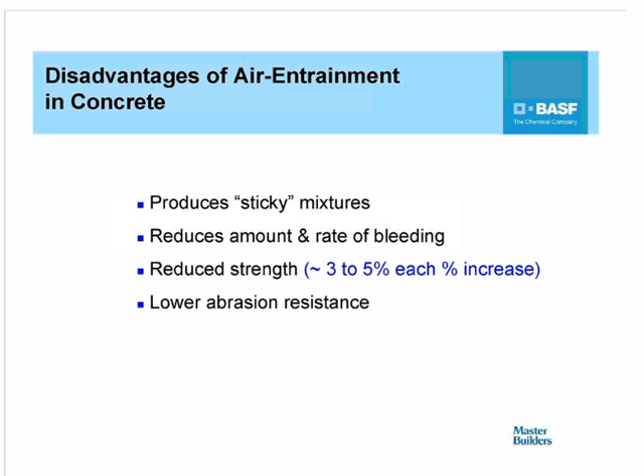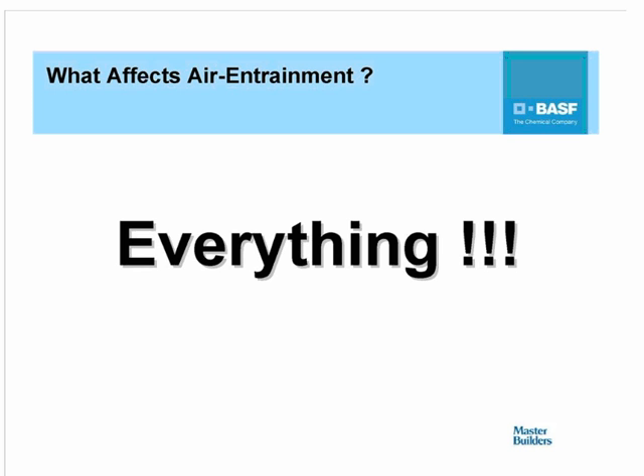Now, the disadvantages of air entraining admixtures in concrete basically include the fact that sometimes the mixes can be sticky, and in addition, because of the air bubbles, they tend to reduce the amount and rate of bleeding. Now, in addition, entrainment can reduce the strength of the concrete, approximately 3 to 5% for every percent increase over and above what the concrete was designed for. And entrainers may also lower the abrasion resistance depending on the effect that they have on compressive strength.